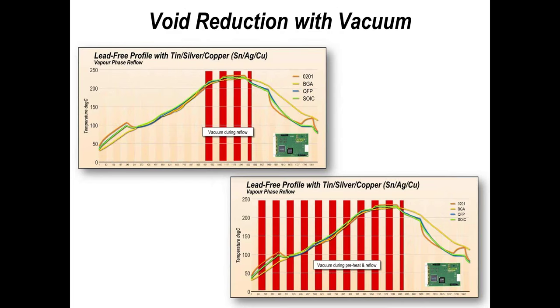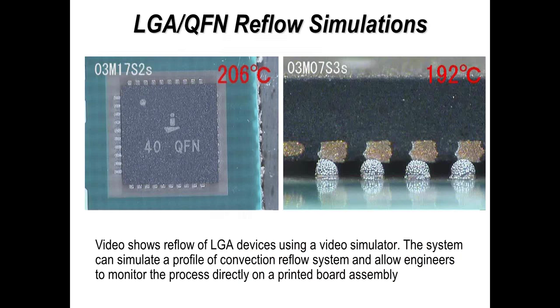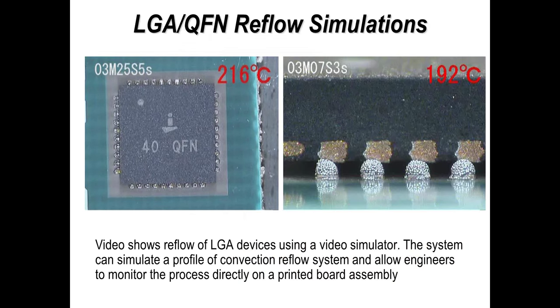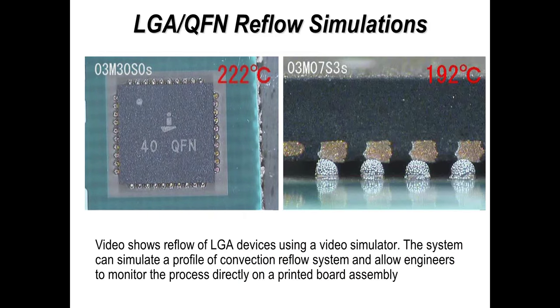And what I'm just illustrating here is how you can use vacuum. Vacuum when the solder is in a liquid state, or theoretically, we can bring in a vacuum right from the start of the reflow cycle and change the vacuum as we go through the process. But the key thing with this type of technology is making sure we do it slowly. Never pull a vacuum fast. Basically, you're sucking air out of solder paste, which is trapped underneath a component. If you do, you'll have a problem.